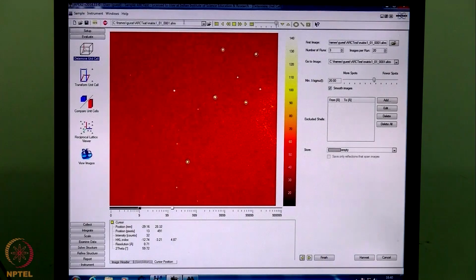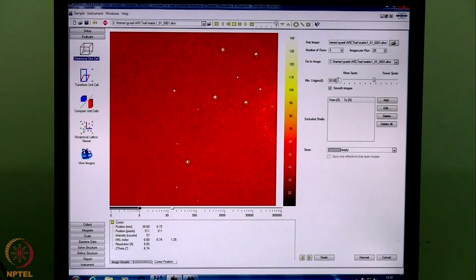So now the initial frame recording is over and it has brought us to this window. What we can see here is that some spots are circled with green and some spots are not. This is because the mean I by sigma set here is 20, which means only the very strong reflections are selected. If we make it 10 and press enter, then it selects some of the weaker reflections also. If we make it 5, it will go down further and select some other weaker reflections as well.